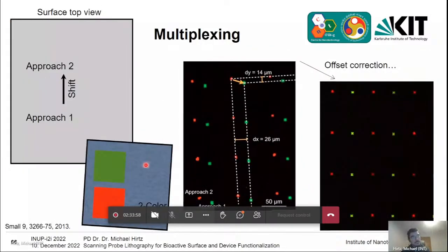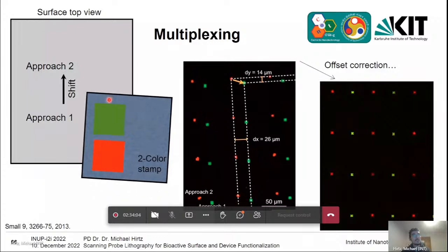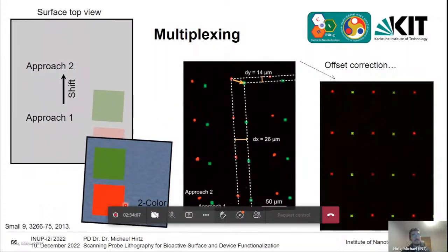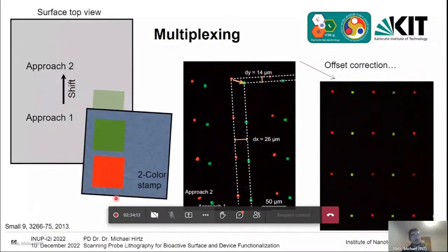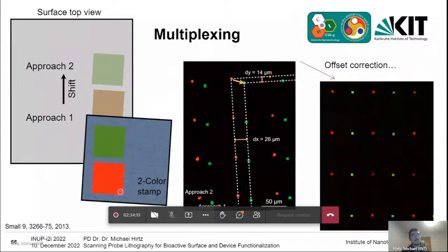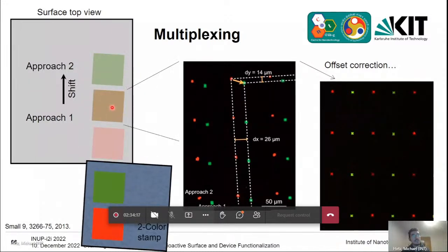Again, we can also do multiplexing with this. And this works by applying a subsequent stamping. So if we have a two-color stamp and we stamp our patterns only once, you get your pattern in one color or the other color. But now, because of the precision of the stage, we can move with a second color over the first color, and we can get these kinds of multiplex patterns.